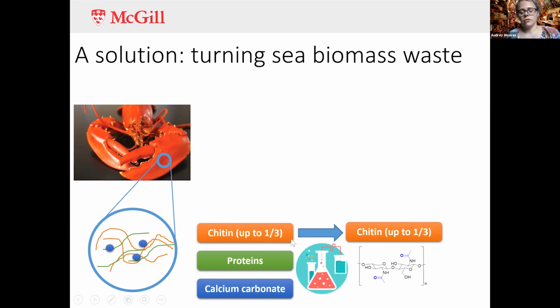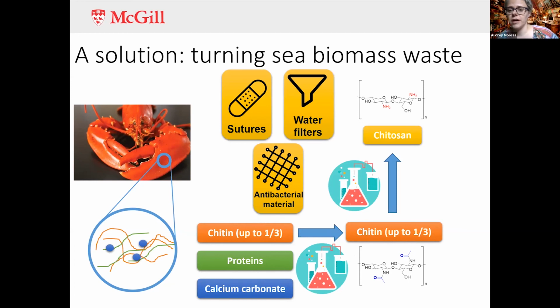So what you'll do is extract chitin from the rest, and that calls for the use of a lot of chemistry. So you usually will expose them to corrosive materials and heat. Then from chitin, it's a good material, but you can actually turn it into chitosan, which is an even better material as it has a lot of cool applications in sutures, water filters, or antibacterial materials, and so on and so forth. But the issue with this is that it really calls for very dirty chemistry.